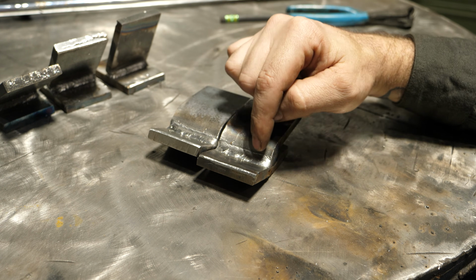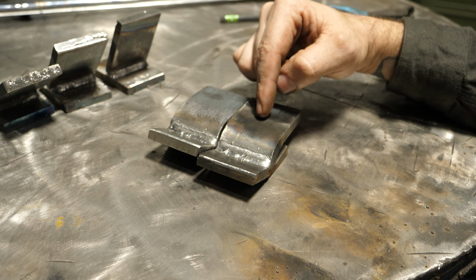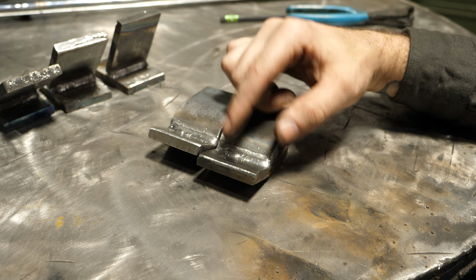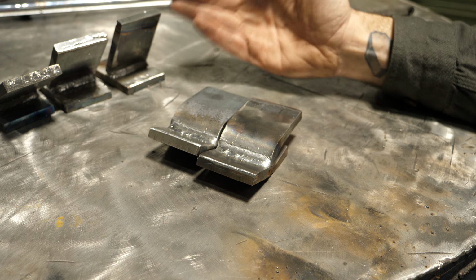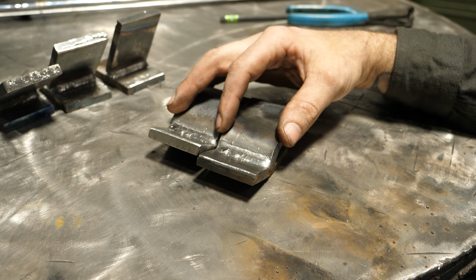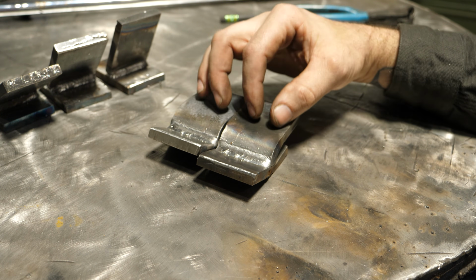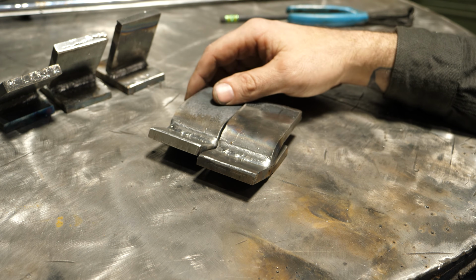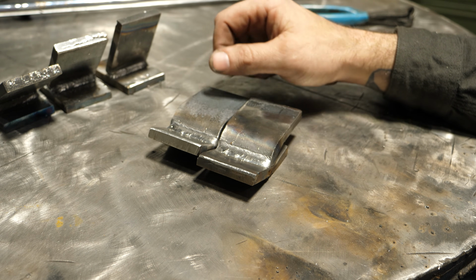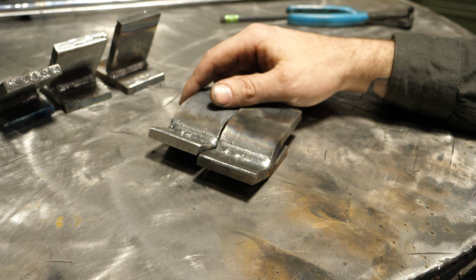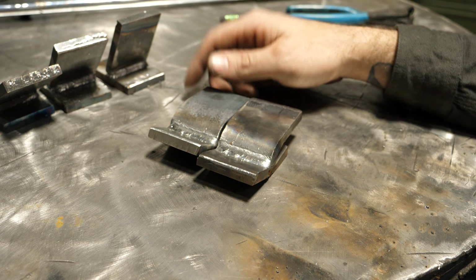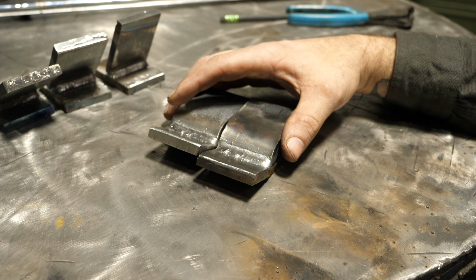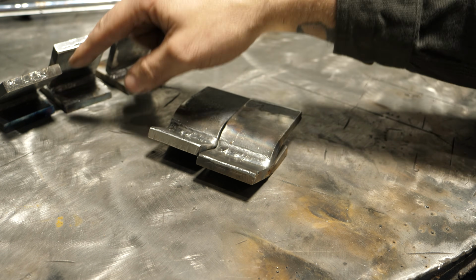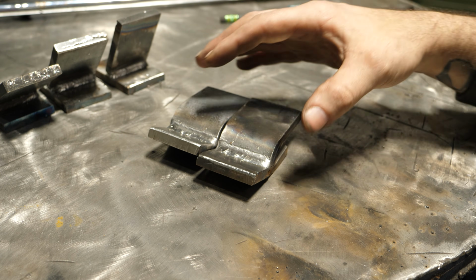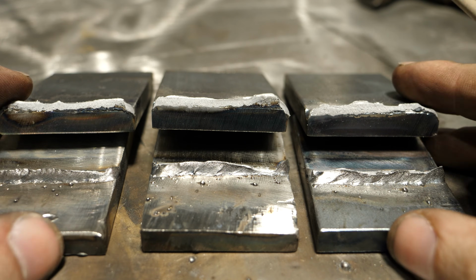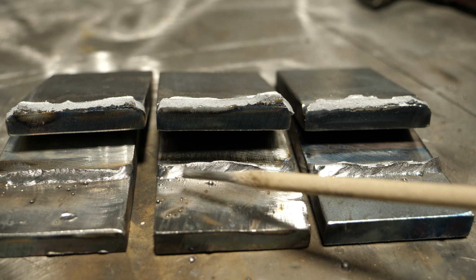And that doesn't mean that you can short arc MIG 3/8 all day. Really, you shouldn't be doing that, because, well, you saw there were differences when we bent it towards the face. But not only that, over time, yeah, this has a tremendous amount of strength the way it is. However, if this plate was subject to vibration or continuous stress, having an undersized weld in the long run would likely crack or fail. So just certain things to think of. But let's go, and I'm going to break these the rest of the way, and we'll do a close-up look at those. So let's take a look at what we got on these where we bent them to the face.